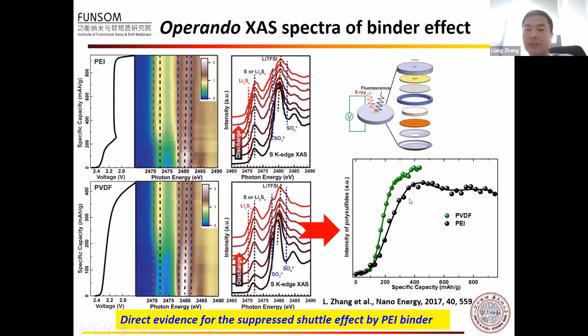However, if we plot the intensity of the polysulfide for the PEI and the PVDF binder, we can clearly see the difference. For the PVDF binder, we can clearly see the continuous increase of the polysulfide intensity, which indicates the sulfur is first converted to the polysulfide, and the polysulfide is easily dissolved in the electrolyte. However, for the PEI binder, the intensity increases initially and then slightly decreases. This indicates that part of the polysulfide can still be dissolved in the electrolyte, but at the end of the discharge, part of the polysulfide is converted to the lithium sulfide. So the XAS result here provides very direct evidence for the suppression of the shuttle effect for the lithium-sulfur battery.